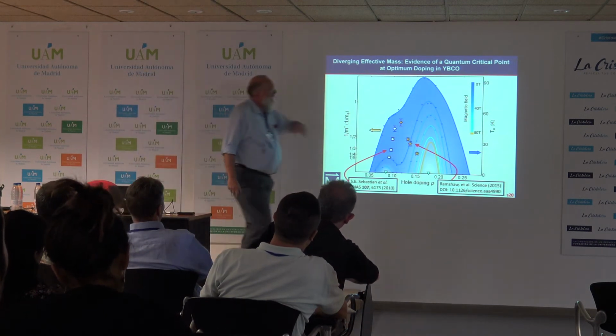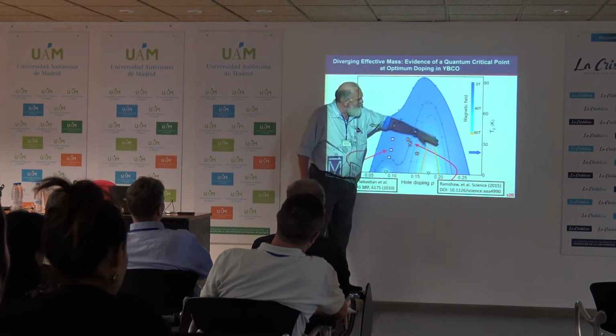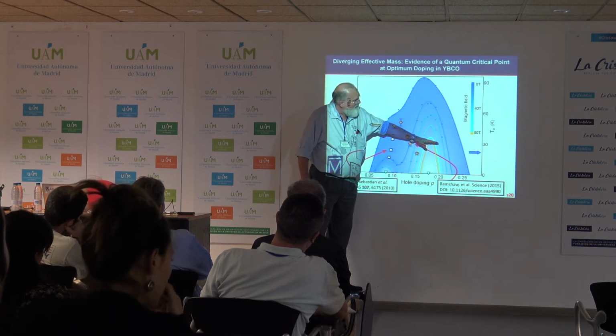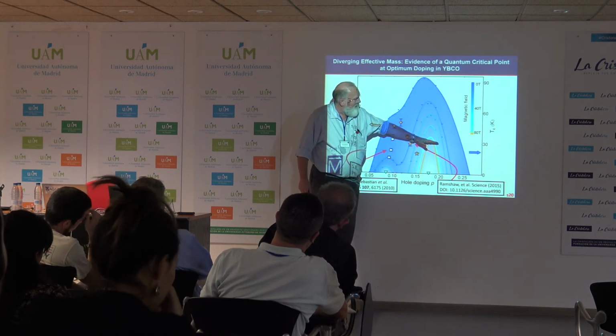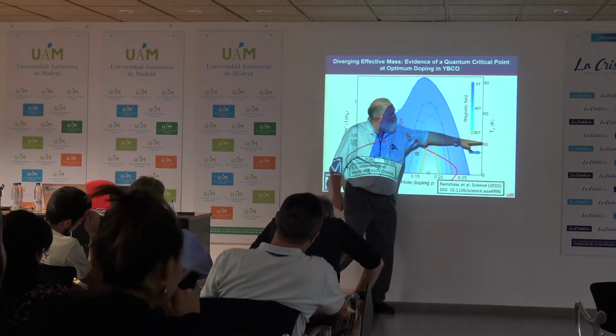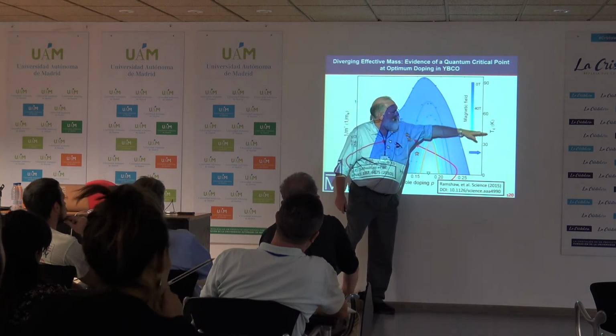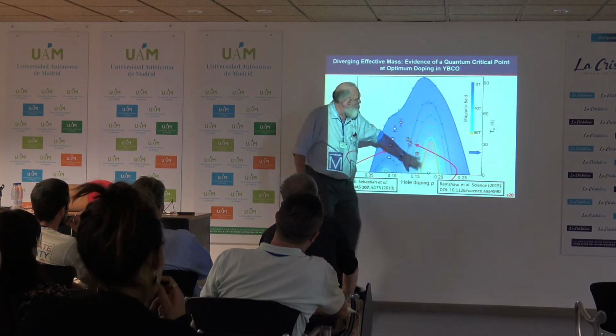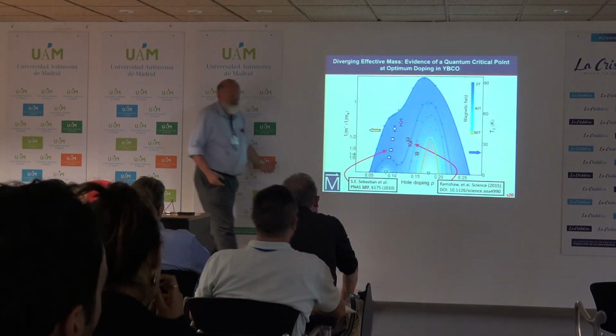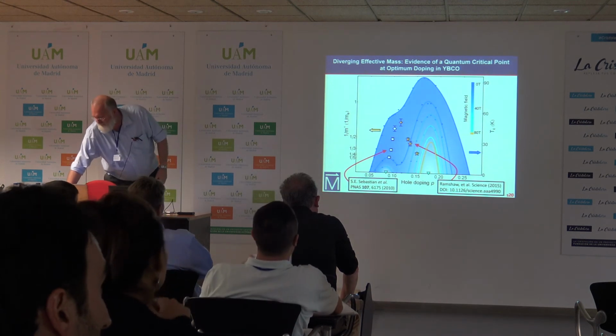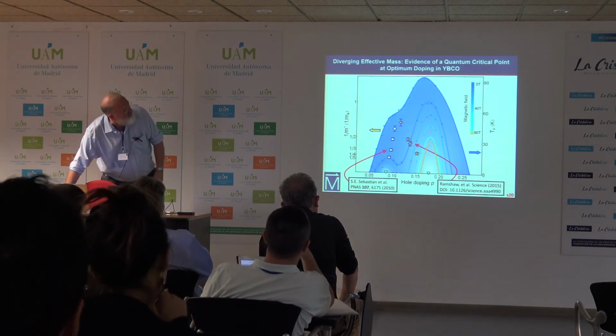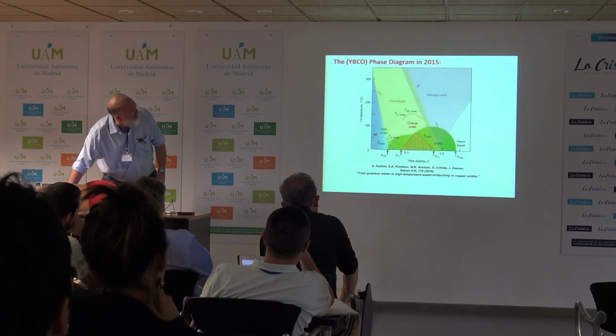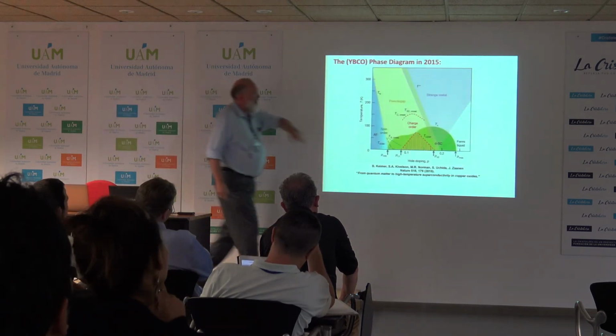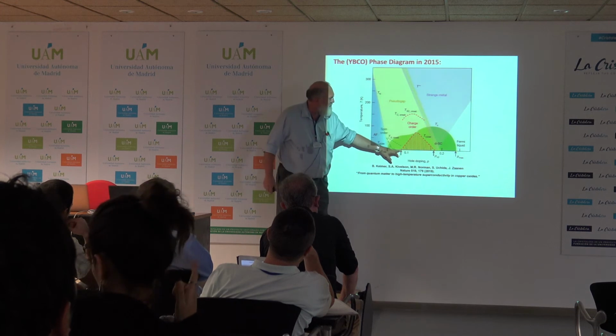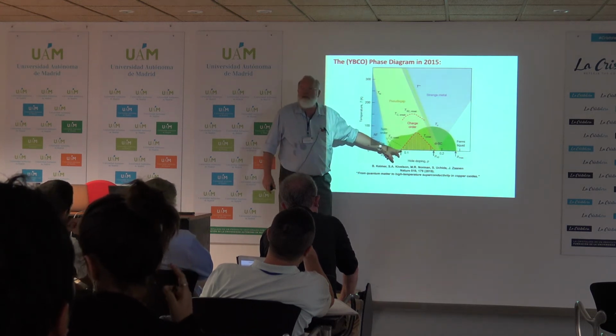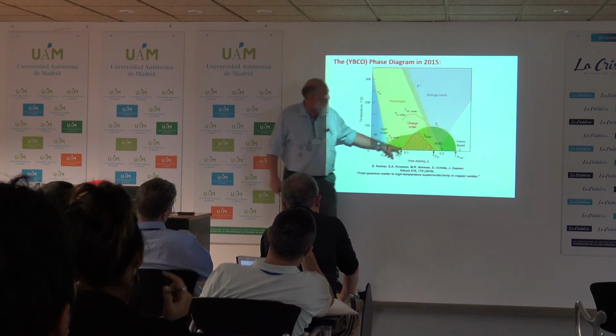And the other thing to point out, as I pointed out earlier, at 80 Tesla, you still cannot suppress the superconductivity below about 35 Kelvin. And this is the zero resistance state. So the transition takes you even higher. This whole area gets obscured because of the robustness of the superconductivity. And even 100 Tesla doesn't suppress it much more than that. So we need bigger magnets. So this is the phase diagram I showed you, and lo and behold, these are the 2 points that show a mass divergence in YBCO, where you've got the ends of this charge density wave ordered state.